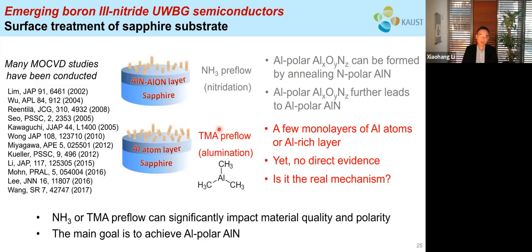Basically in this technique, people flow trimethyl aluminum, again one aluminum with three methyl groups, before the growth of aluminum nitride. And some researchers hypothesize that a few monolayers of aluminum atoms, or an aluminum-rich layer, are formed during the preflow process. And then on top of that, if you do the growth, you will have aluminum polar aluminum nitride. However, there has been no direct evidence to support this hypothesis. Also, it would be very amazing if a thin layer of metal could be formed between one insulator and one semiconductor, right? So we wonder if this is a real mechanism, because this is very important to grow high quality aluminum nitride on sapphire.